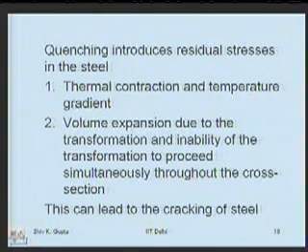Well, that's what I was trying to tell you. Quenching introduces residual stresses in the steel. And the reasons I gave you were, one, the thermal contraction, and second, the transformation of the matrix, which again is not uniform. It is not the whole volume; part of the volume is transforming. And that is why residual stresses lead to the cracking of the steel.